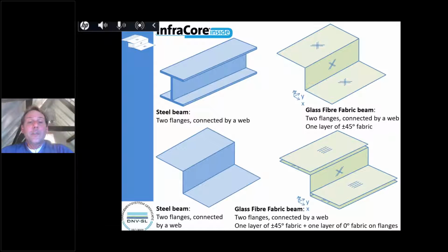And what we did is we translated this Z profile into the upper right composite profile, which is identical. It has identical material properties in all directions. But if you want to morph that to have dedicated material properties in a particular direction, you go to the lower right and you just add fibers in a particular direction. So what we did is we started with the classical I-beam, morphed it to a Z, and we add additional strength and stiffness in the directions that the end application needs.